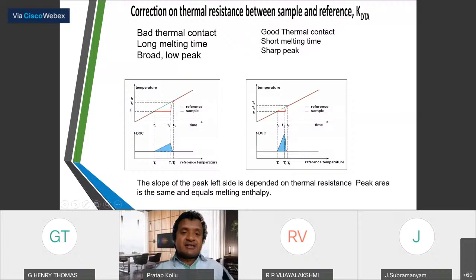So something like that. So the time will be long, and the peak will be really broad, and it will have less intensity or less height. So if it is a good thermal contact, the peak will look like this. A sharp peak with very good intensity, high intensity or amplitude, and the time is very less. So here the slope of the left peak is dependent on the thermal resistance, peak area, and it equals the melting enthalpy.